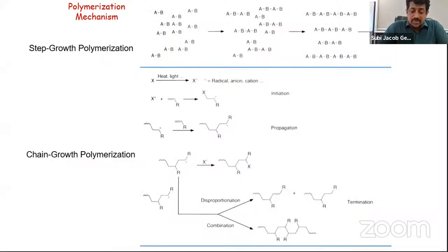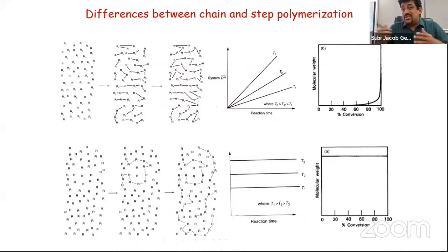Many groups started looking into the mechanistic aspects of supramolecular polymerization. We know that in polymer chemistry the mechanistic aspects are well understood. We have two types of mechanism: one is step-growth polymerization and the other is chain-growth polymerization. The mechanism by which polymers are made plays an important role, because the degree of polymerization, the molecular weight and the dispersity highly depend on what kind of mechanism you use. For example, in step polymerization, to get a high degree of polymerization in a typical condensation reaction, you have to push the reaction to almost 100%, or 99.99%.